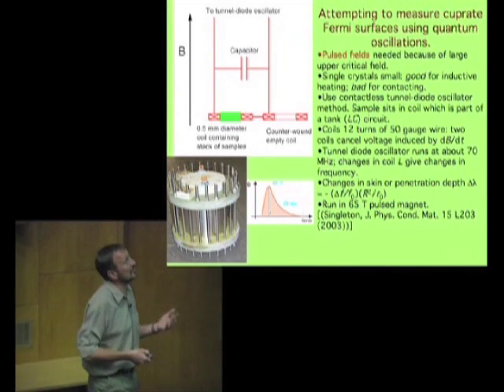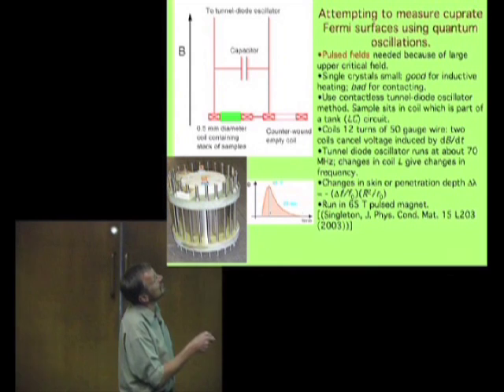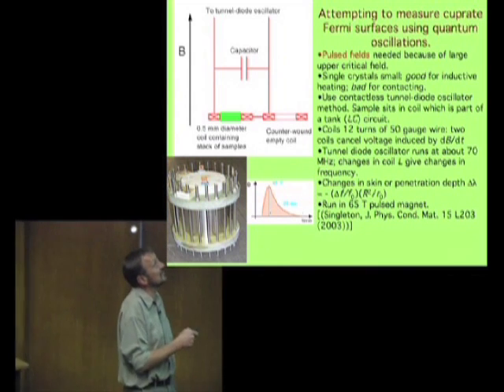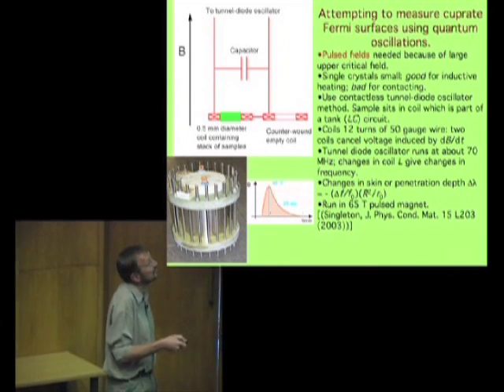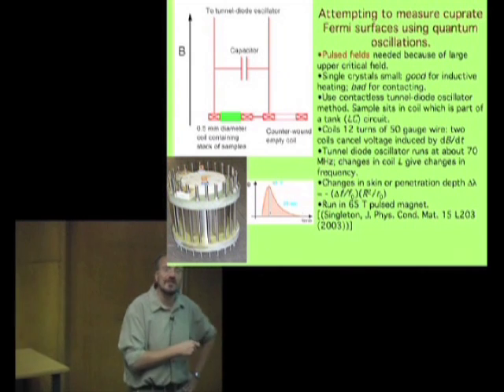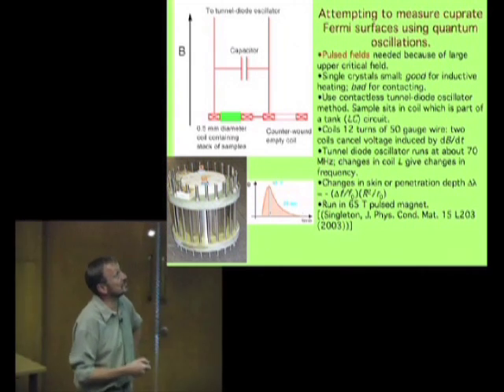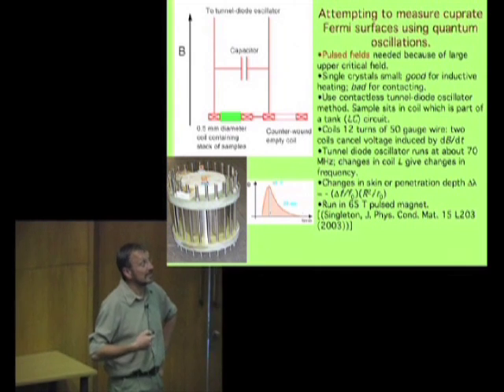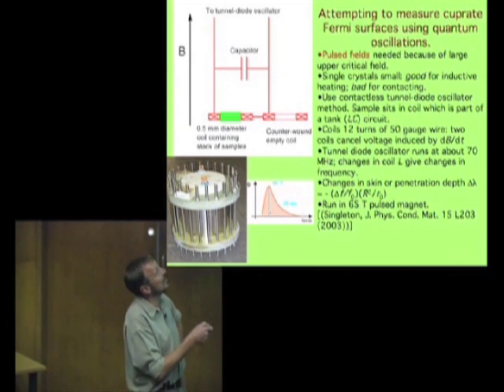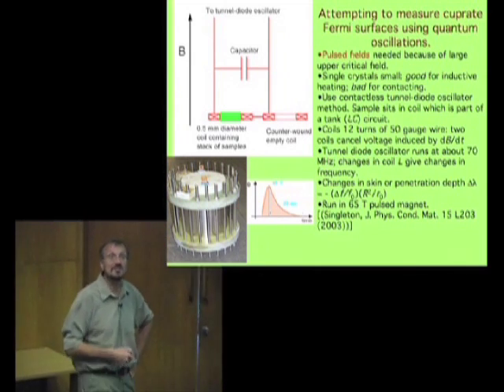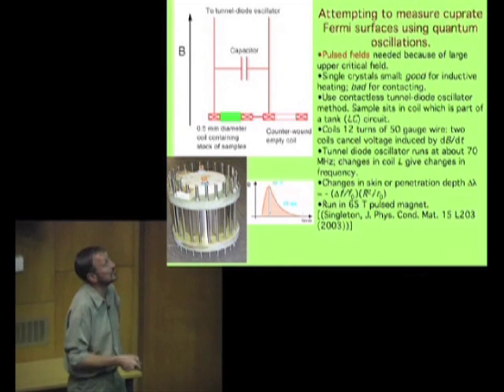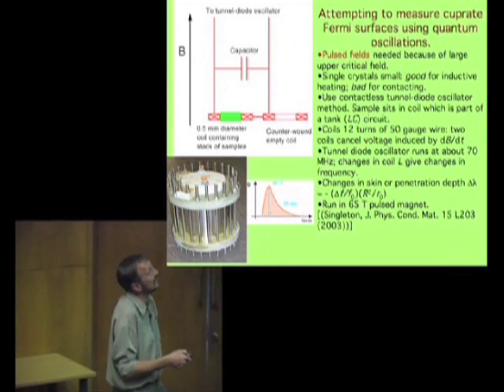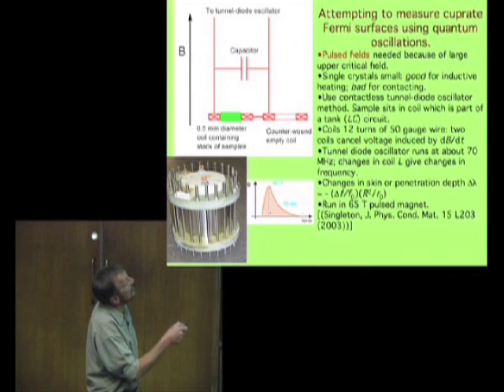So now we want to go on to the cuprates. We want to attempt to measure the cuprate Fermi surfaces using these quantum oscillations of the properties. So first of all, because the high temperature superconductors have these high critical temperatures, they also have very high upper critical fields. And to measure the properties, you remember from the organic superconductor, we need to get it into the normal state. So we need to use very high magnetic fields.